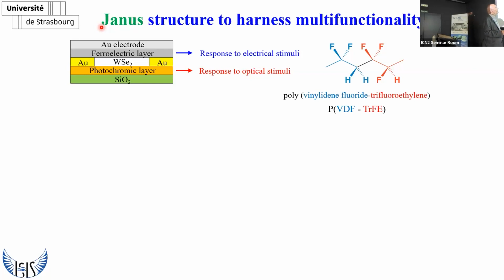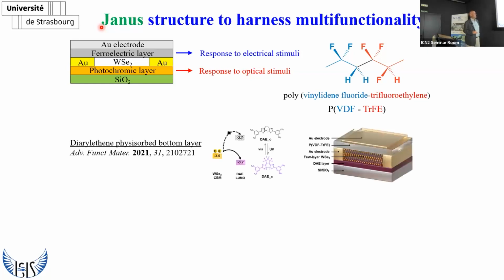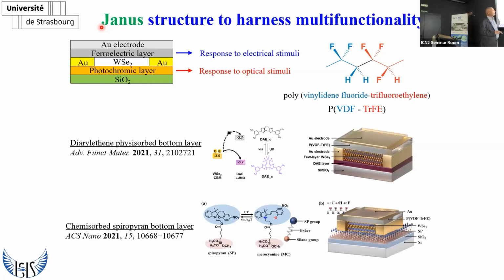For the ferroelectric layer, we did not reinvent anything. We use polyvinylidene fluoride trifluoroethylene, which has been used thoroughly in organic electronics, for example combined with polythiophene, in order to fabricate devices that respond to an electrical stimulus. And this approach we have been using and reporting in different papers. The difference is essentially what kind of photochromic molecule we have been using.